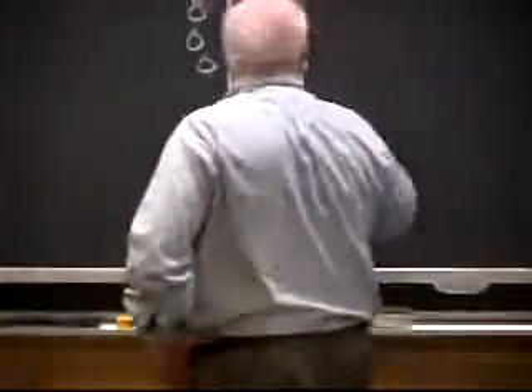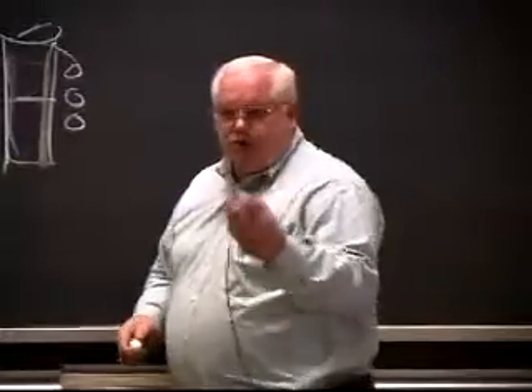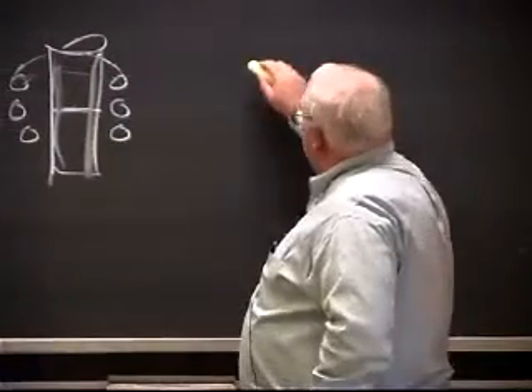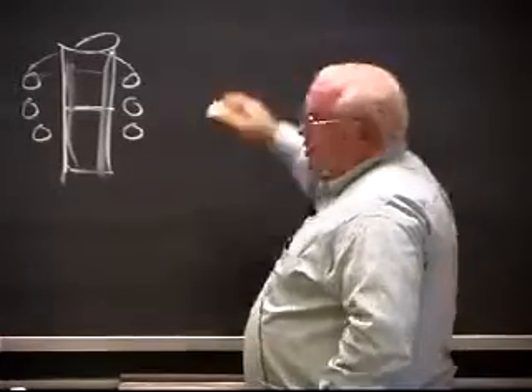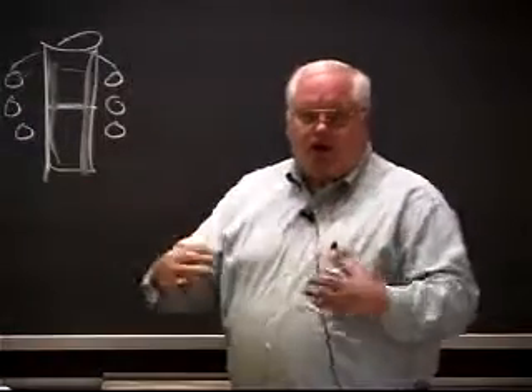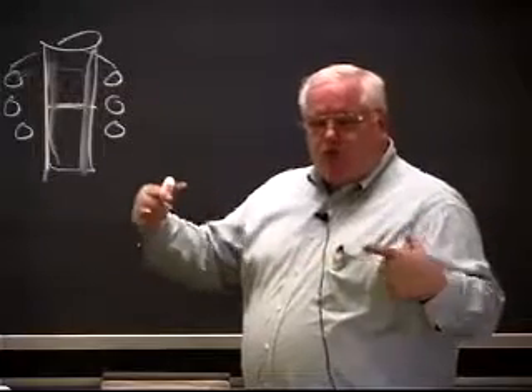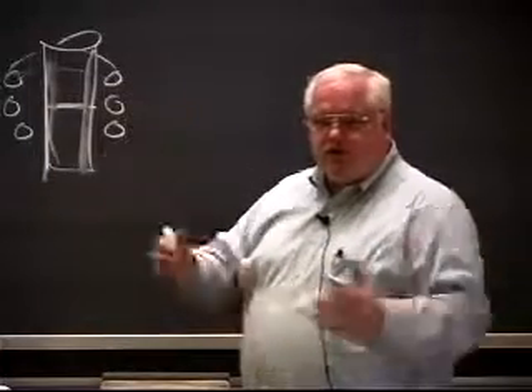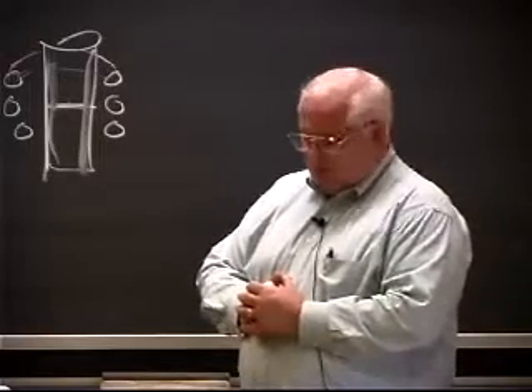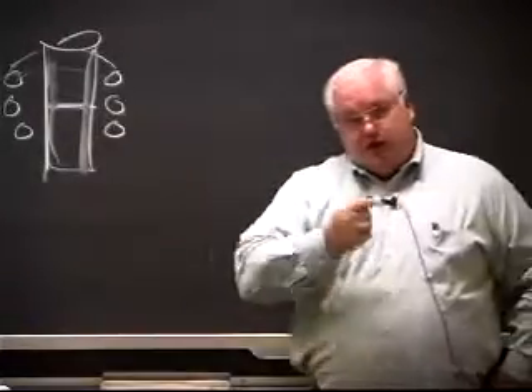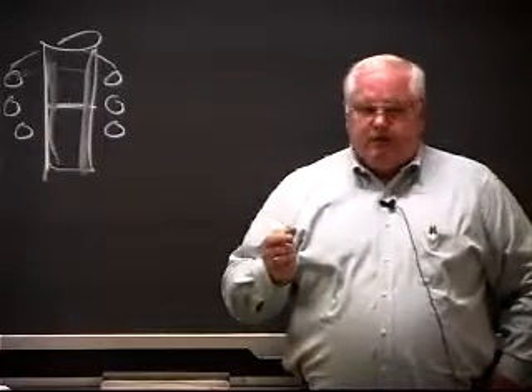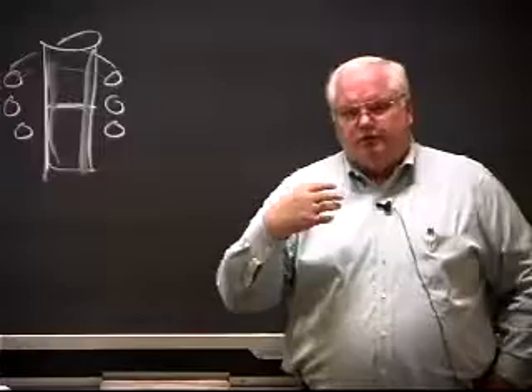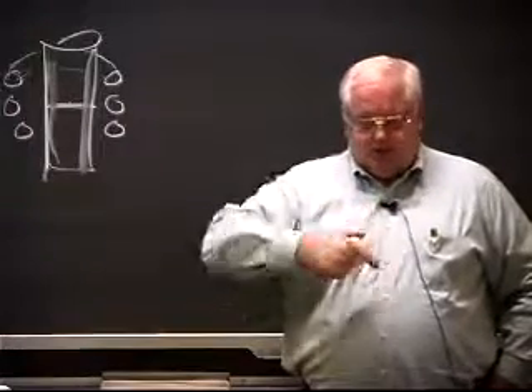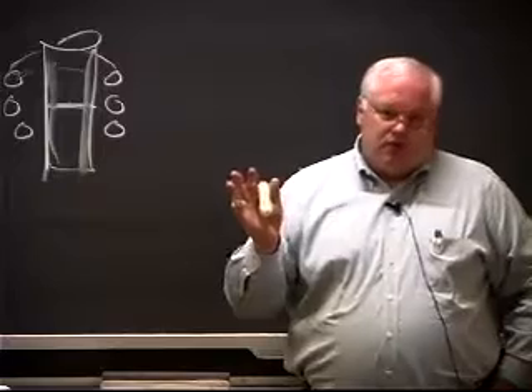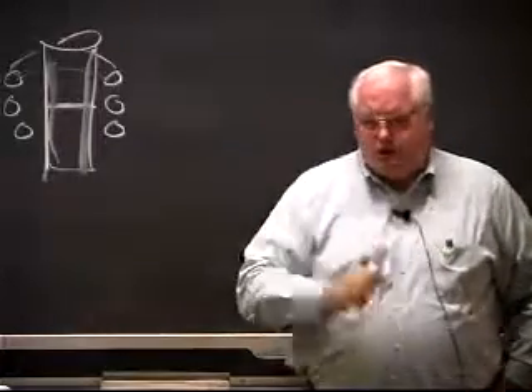In fact, one time we were worrying about brazing porous graphite, and the porous graphite were essentially tubes, and they used it for filtering, very, very fine filters in these graphite composites. They would start out with a plastic cloth and weave it together and then wrap the cloth into a circle and then put it in a furnace and bake off all the stuff and graphitize this polyacrylonitrile plastic and end up with a porous graphite substrate. And then they do some other things to control the pore size so that you'd have a filter and you could pump a fluid in one side and get your solid particles to go out with your influent stream and get the clear liquid come through the pores.